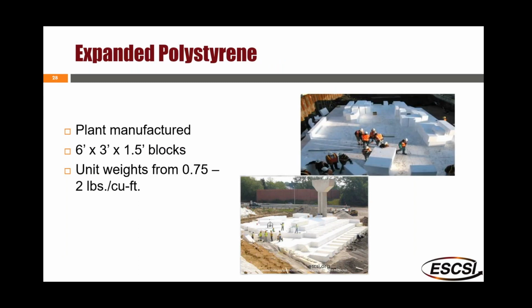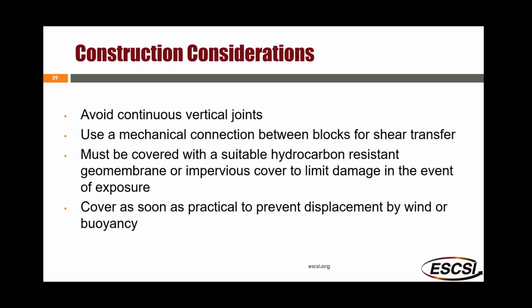Taking a brief look individually at a few of the lightweight fill options on the market today. Expanded polystyrene is one option. It's a plant manufactured material, usually in 6x3 by 1.5 foot blocks, with unit weights that range from 3/4 to around 2 pounds per cubic foot. Some construction considerations for this option include you have to avoid continuous vertical joints, so the blocks need to be laid in a running bond, similar to the way you do a brick veneer. You use a mechanical connection between the blocks for shear transfer, so that has to be installed.